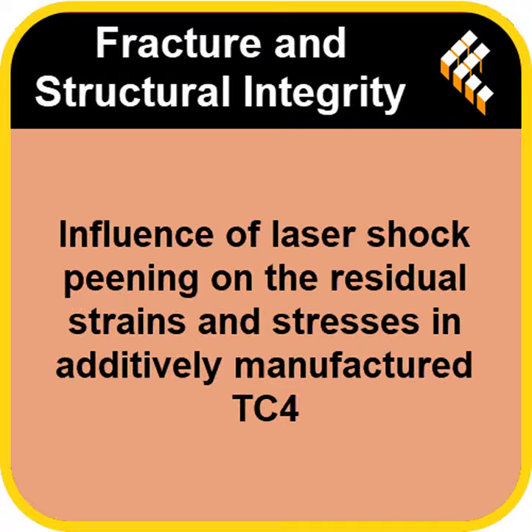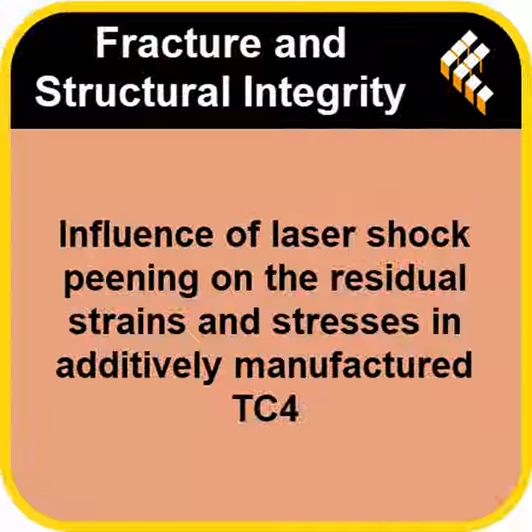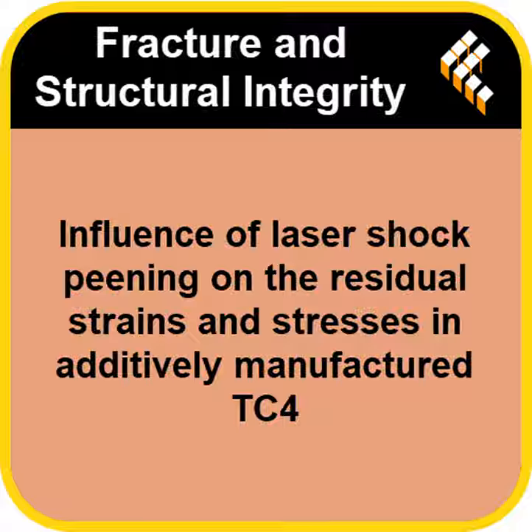Wow, less than 10% error. That's pretty accurate validation. It's excellent validation. It means the model is trustworthy. So what's the real-world value? Why build this accurate digital twin? Because now you can use this validated model to predict the stress state in parts where you can't easily measure it physically. Like what? Think about really small parts, like tiny medical implants, or components thinner than the hole drilling method allows, say, less than a millimeter thick, or parts with really complex curves and features where you just can't apply a strain gauge properly.